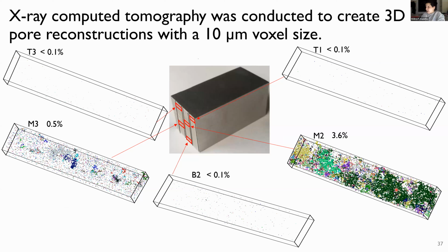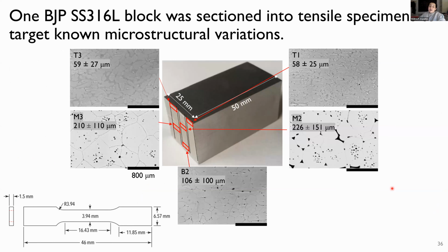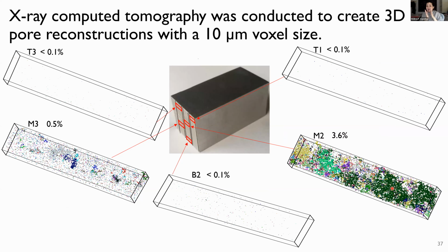So what you're seeing here on the right, each of the pore networks is colored by an individual shade. Everything that you see here in the dark green is actually a pore that connects the whole way through. In the thickness of the sample that we were dealing with, which was 1.5 millimeters, the pores actually extended from edge to edge. The chances are that the pore network was actually extending significantly outside of that plane as well. So this was already pretty informative in terms of what was happening in the behavior of these parts.